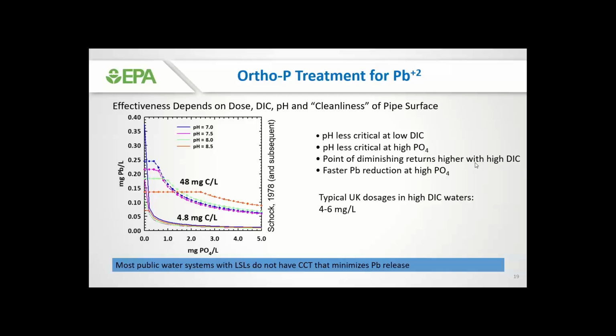The effectiveness of orthophosphate really depends on the dose, the underlying DIC and pH of our water, and also the cleanliness of the lead pipe that we actually have. This is, again, theoretical lead solubility calculations depicted on the graph. On the x-axis, you can see the phosphate added in milligrams per liter from 0 to 5. And on the y-axis, you can see lead solubility in milligrams per liter of lead. So again, we really want to minimize lead solubility on the y-axis to be at the absolute lowest point of any of those curves. The different colors depict different pHs from 7 to 8.5.